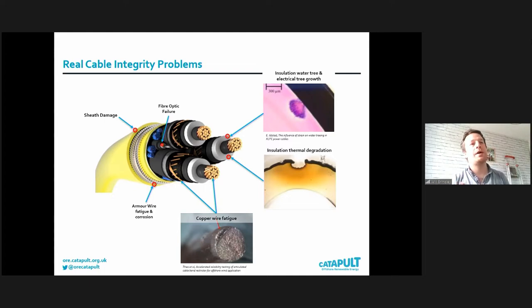And the other thing that affects the behavior of the cable is temperature. So power cables, lots of current heats up the cable. When the cable gets hot, it gets less stiff because of how the polymers behave. So then you get higher curvatures on components. And some data indicates also for copper that you have about 10 times higher fatigue damage when it's hot as well. So there's an interesting coupling there between thermal and mechanical stress. And the other thing that doesn't do well when it's hot is insulation. So designing insulation to behave well and making sure it doesn't overheat would be a big challenge, particularly when you've got big bend stiffeners and the cable as it goes into the vessel where it might be quite well insulated.